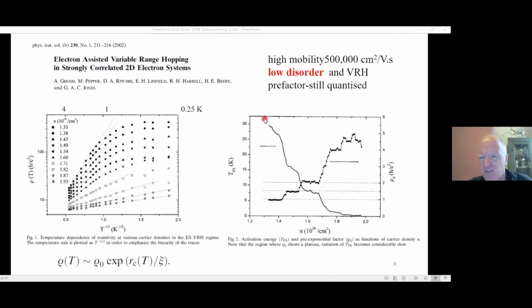Some more detail on this. There's a little bit more experimental background here. This work can be carried on in high mobility materials, not necessarily induced disorder, but intrinsic disorder in the system due to just regular doping. So a high mobility device, which has low disorder, but if you go to low enough carrier densities, a few times 10 to the 10, the prefactor is still quantized. Although you haven't introduced disorder, the prefactor is still quantized. So this is the Efros-Shklovskii mechanism in this much more lowly disordered system.